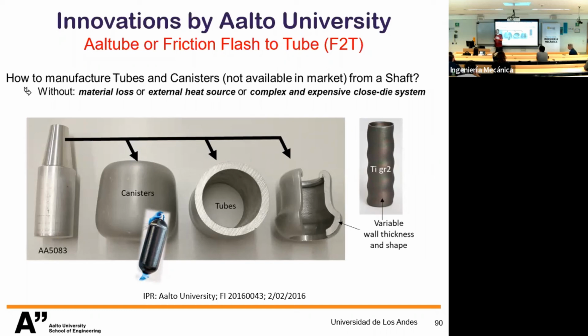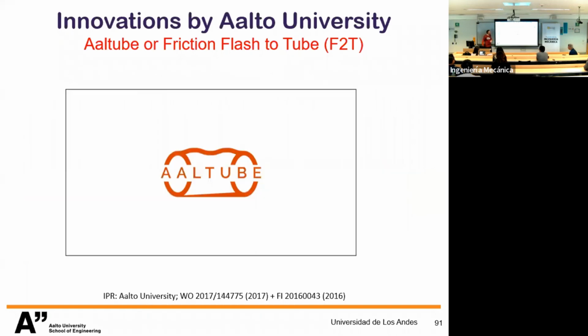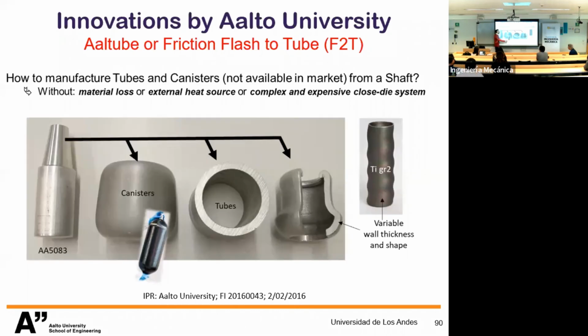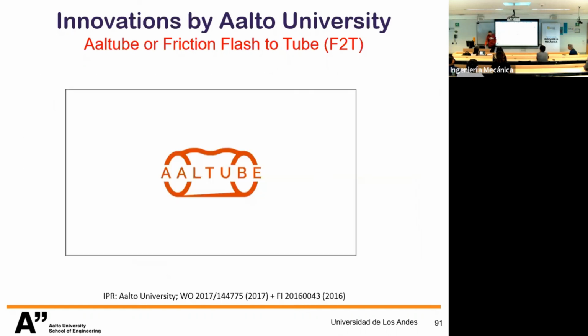Tubular shapes are produced by this complex welding process of forming and welding, okay? Or then they have to be extruded, and in steel, they are for large cross sections. They are extremely difficult to produce. And so the amount of tubular system, and they are producing a big amount of tons, are the minimum amounts economically viable to be produced. We can produce it in several materials, in stainless steel, aluminum, titanium, as you see here. We can produce it with uniform thickness, different thicknesses, varying the shape.